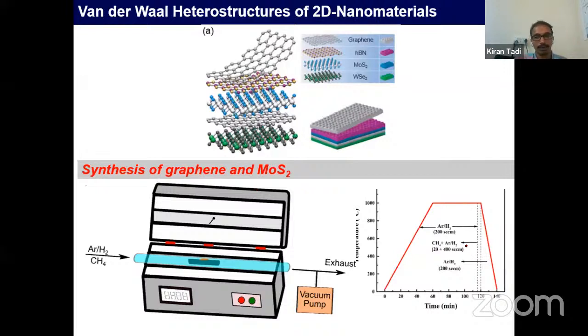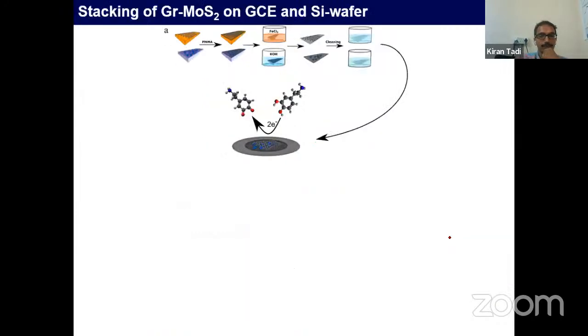There is a bottom-up approach, and this is a CVD synthesis where we controlled the temperature, time, and gas flow. Once we did this graphene and MoS2 synthesis, we transferred it onto the glassy carbon electrode using the wet chemical etching method. It is a very sensitive method; we have to do it very carefully because handling the monolayer graphene during cleaning and etching the surface of the copper and silicon is involved.